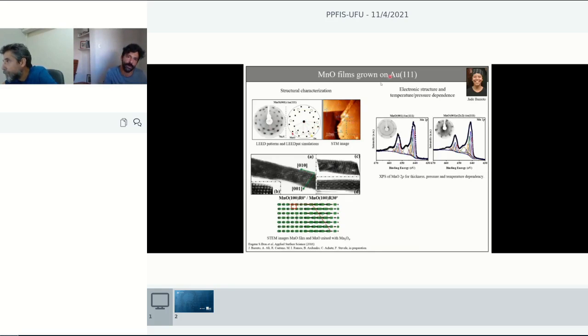Here you also see a part of the substrate that is not covered, and this is useful for us to judge the height of the structure that we are seeing. Because we have directly a step edge here of the gold 111, we can judge, as an internal calibration, the height of these islands here. What is interesting is we can change the properties of this film, change the deposition procedure, and also the amount of material that we deposit, and then obtain relatively thick films that serve us as a model.